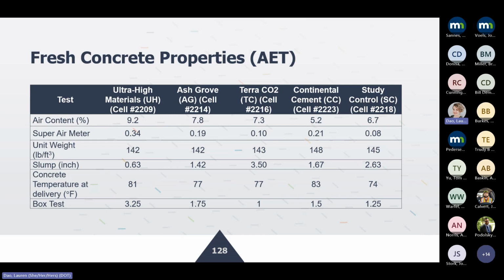They did add the viscosity modifying admixture. They didn't have the right quantity of the water reducer, and there might have been some contamination at the batch plant, which resulted in a very, very stiff mix initially, but they did improve the mixture as we went on. But a lot of the air that you see there is probably entrapped air.